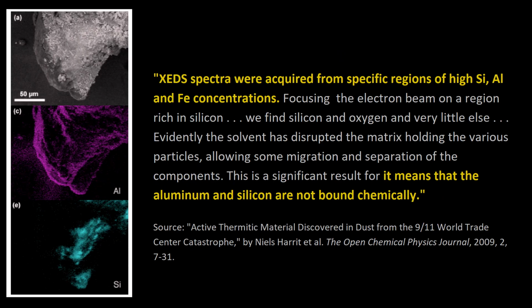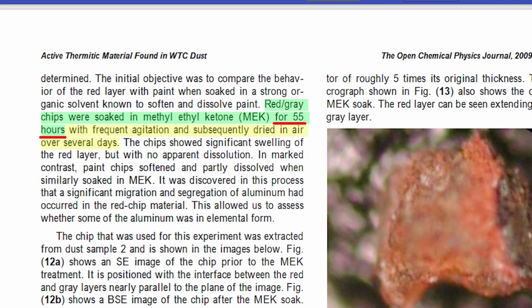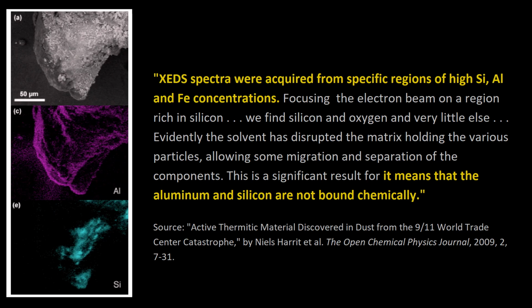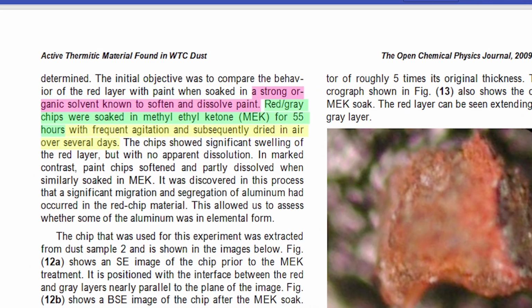Yeah, right, dude. I'm sure that aluminum just flaked off from your tinfoil hats or something. No, I see a major problem with their analysis here. They subjected the red chips to 55 hours worth of soaking in methyl ethyl ketone, which we're told is, quote, a strong organic solvent known to soften and dissolve paint, end quote. Isn't it possible that the aluminum has merely dissociated from the silicon as a result of being subjected to this strong organic solvent, which is known to soften and dissolve paint?